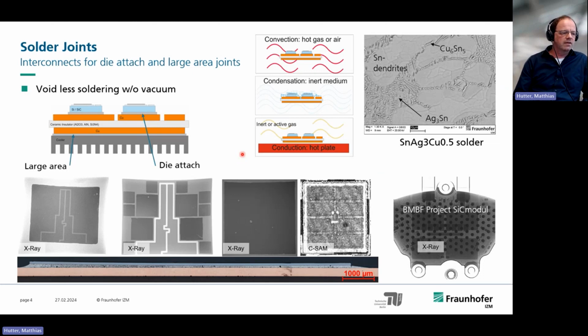The most important thing with the solder joints for power electronics is that the solder joints have to be more or less voidless. So we have to have processes where we get rid of all the voids or don't form voids in the first place. So we have three different kinds of soldering. We have the convection soldering, where we heat everything using a hot gas or air. We have the condensation soldering, where we use an inert medium which condenses on the power module and transfers the heat then to the module. And we can also use a hot plate, a conduction soldering, in order to form a die-attach solder joint or a large area solder joint.